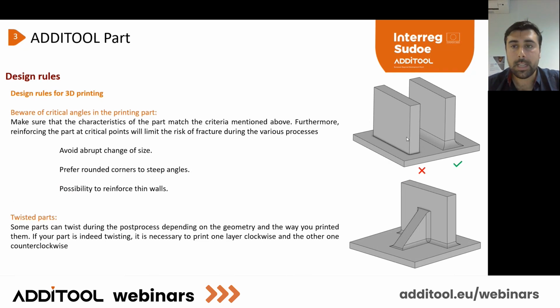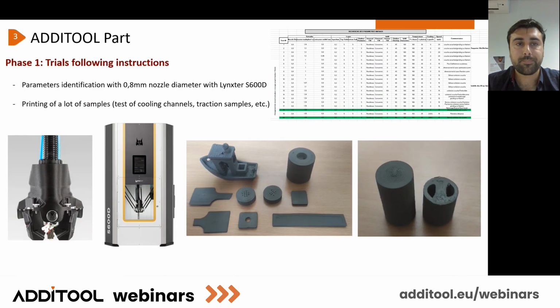Something important also is to beware of critical angles. It's true for every process, like machining, like metal additive manufacturing. Prefer to use some chamfers, some curves in the edges, to avoid abrupt changes of size. And also, don't hesitate to put in some stiffeners like this to avoid a twisted part, after debinding and sintering.